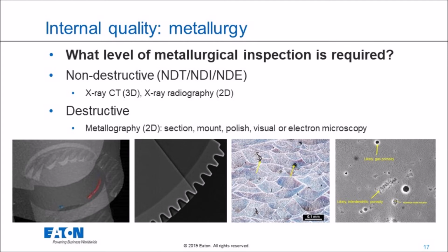So then maybe you can go to X-ray radiography. What this gives you is essentially a 2D slice of a CT, where a CT is many X-ray slices built up. From a 2D image like this, you can look at the grayscale formation, and that can tell you a lot about the pore structure and the potential defects in the part. But we also know that depending on how you do your X-ray, you might not be able to catch the small size of pore that you find in a metal part.